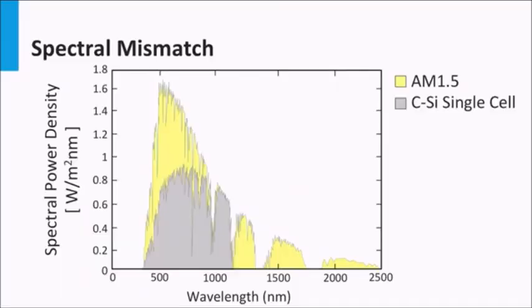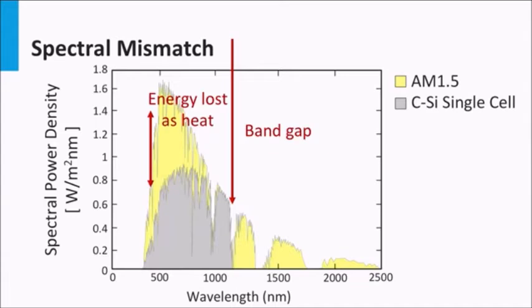Here we see the spectral power density function again. Let's consider the typical optical loss mechanism for a semiconductor with a band gap E gap. Again, we take crystalline silicon as an example. Furthermore, we assume an EQE of 100% above the band gap for the solar cell. Let's look at photons with energies higher than the band gap. We know that we effectively only need energy of the band gap to excite the mobile charge carrier.